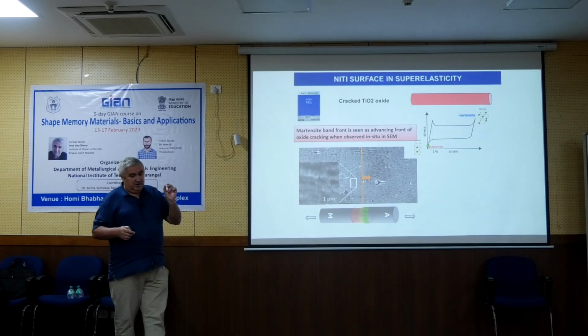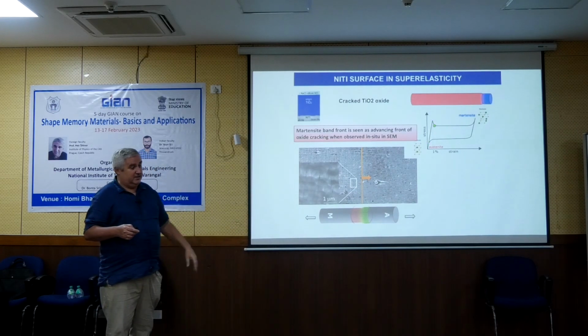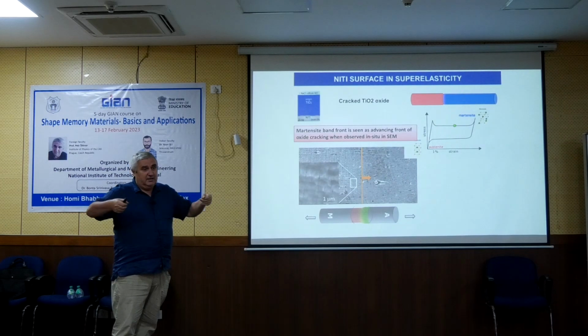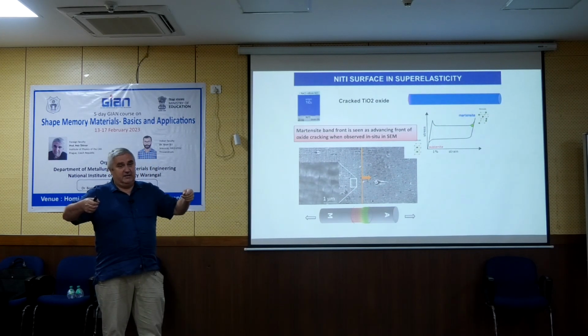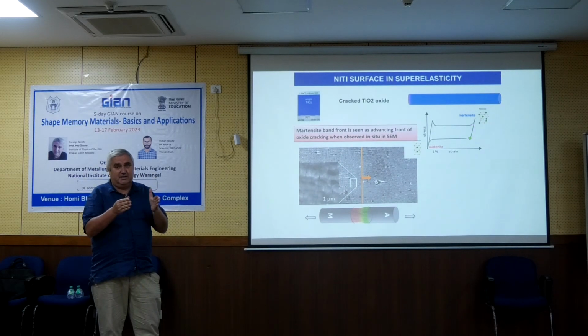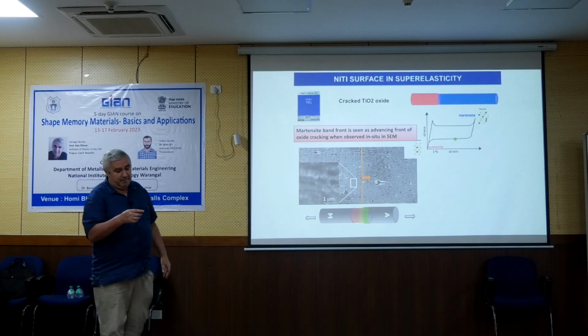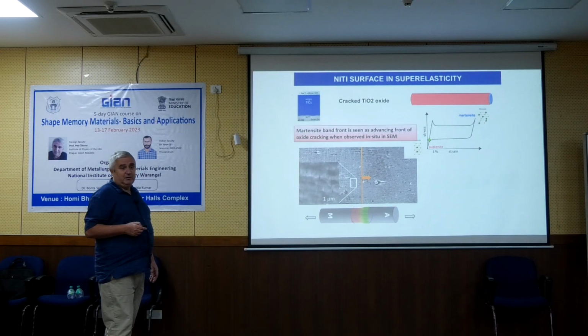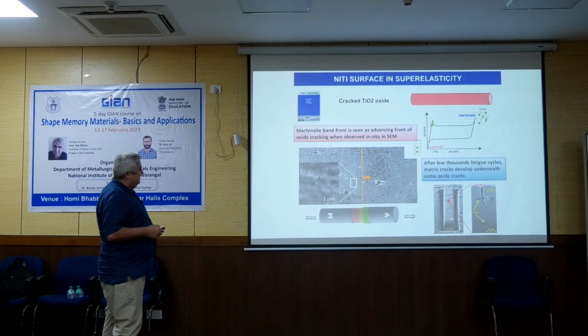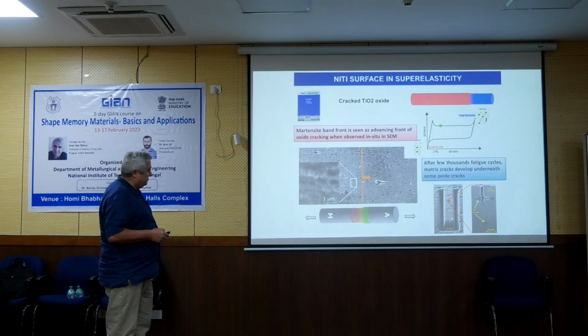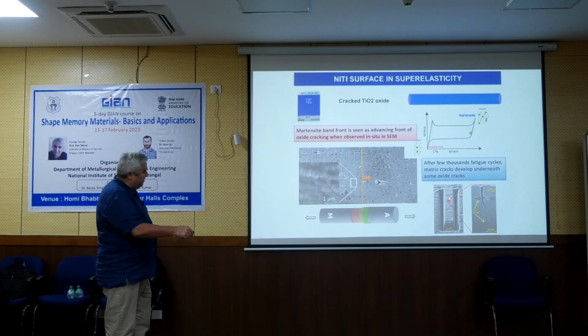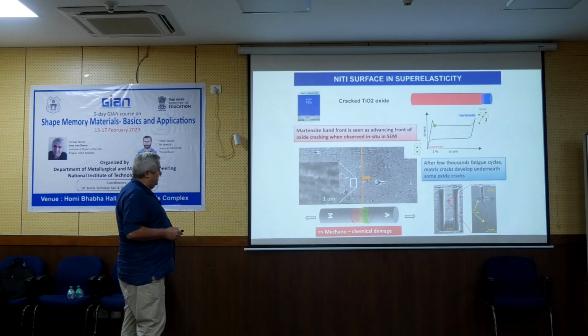So if the oxide becomes very thin, we don't see these cracks because they are too thin. Even if the nitinol is fully stretched 5%, there are millions and millions of very fine cracks which cannot be resolved in the SEM. So you may ask, how do I know about them? I will explain soon. What we also can do, we can extract from the surface a lamella for transmission electron microscope observation, and then look in SEM and TEM at the crack from the side.